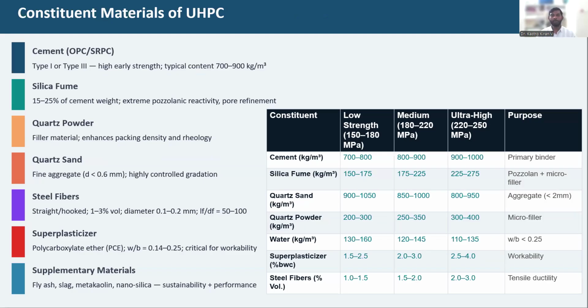And coming to the materials of UHPC, UHPC doesn't consist of any kind of coarse aggregate, which is one of the most important things that we need to keep in mind. Because of the materials that we are using in UHPC, particularly the finer materials, that leads to higher strength, higher durability and dense packing of the materials. And alongside that, it is also important to focus on durability conditions, which most researchers miss out, considering only strength as the primary perspective. Yes, strength is also a good one, but alongside that, it is also important to check the structural performance and the durability performance as well. And practically, we also need to check whether life cycle assessment, life cycle impact, and carbon footprint are also being considered in the design aspect as well.